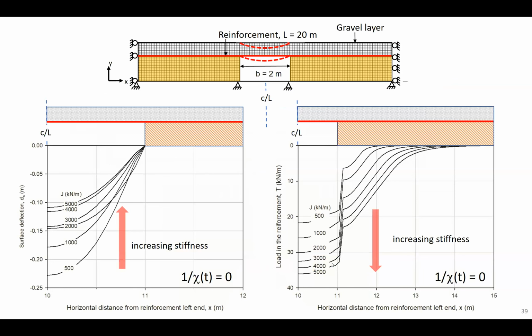So what you see on the left-hand side is a plot of the surface deflection. This is actually the deflection at this point here versus location along this domain. So the middle of the void is right here. And what you can see is as the reinforcement becomes stiffer, the deflection goes down. I don't think this is unexpected, but the point is you can't get this quantitative appreciation from an analytical model. And on the right-hand side that you see here, this is the load in the reinforcement. And again, as the reinforcement becomes stiffer, the load in the reinforcement goes up. Okay, and this is of interest to us because we're interested in a strength limit state calculation or appreciation of this problem.